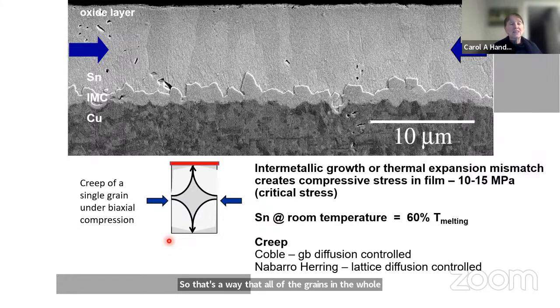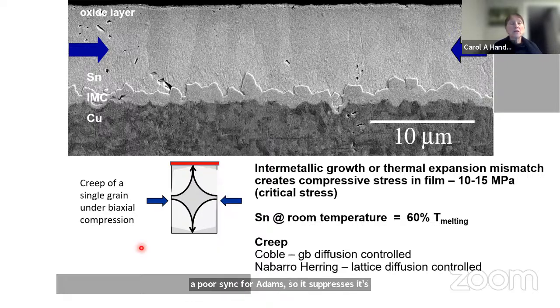However, in the tin situation, tin forms a very strong oxide on the free surface, and it makes this be a poor sink for atoms. So it suppresses Coble and Nabarro-Herring creep. So now you have a film, and you have lots of grains being stressed at 60% of the melting point. And the stress, how is the stress relaxation going to take place?